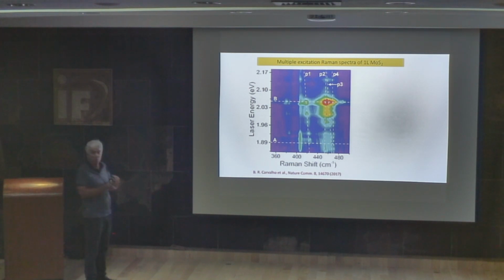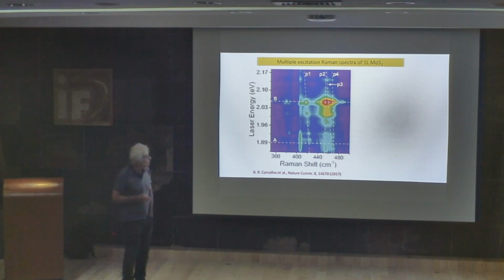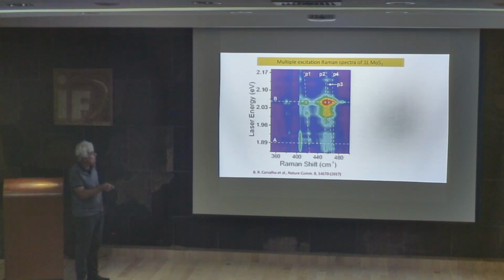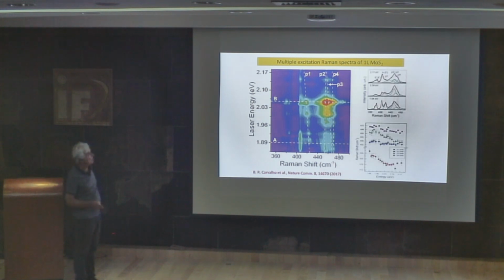Now we are using a tunable laser. This is from red to yellow, but then we can see here the enhancement by the A exciton and the B exciton. But the most important thing that we could show here is that there is also this kind of dispersive behavior. For example, when you have the normal modes like the A and the in plane and out of plane, the position does not depend on the laser, but there are some peaks that depend on the position of the laser, and this is a signature of the intervalley process that I showed you.